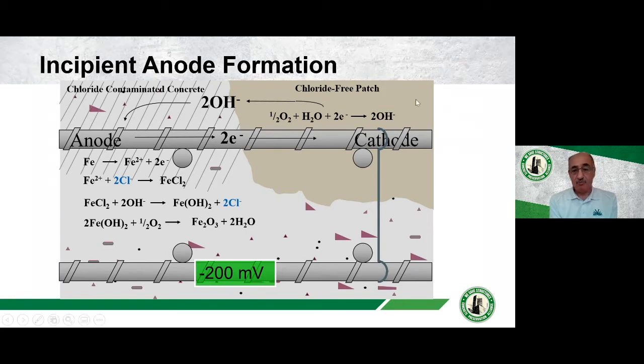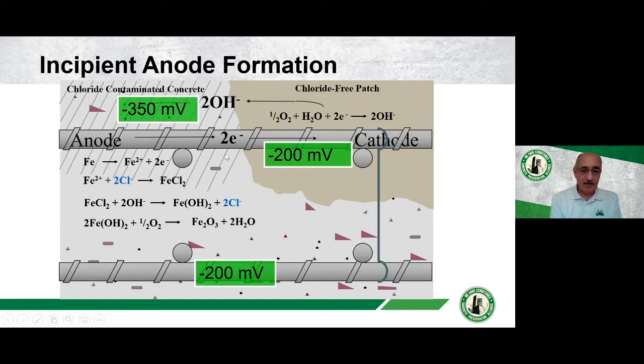So as soon as you apply new fresh concrete onto your steel reinforcement, it's nice and clean, it immediately wants to be the cathode. But if it's a cathode, there has to be an anode as well, and the anode tends to occur on the outside of the patch repair, where you probably still have a little bit of contamination of chlorides, and therefore the potential would take a more negative value compared to what's inside the patch repair. And that obviously is a driving force for the electrons to move across, and you set up this battery, if you like, anode, cathode, and the corrosion initiates pretty quickly outside the patch repair.